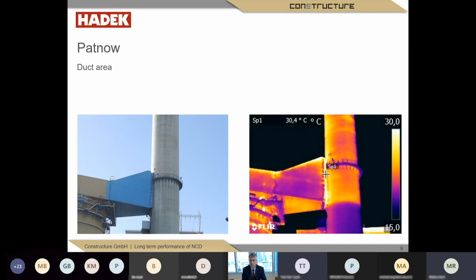On the next page, you can see the thermal imaging of the duct area. What you can clearly see is the area where the inside surface is subject to hot flue gases, because below the hopper, everything is cold. And above you have a uniform temperature distribution on the surface, and we detected no suspicious areas where the Penguard block lining failed. Here in the compensator area, you can see that there is a lack of insulation, and there the temperatures are a little bit higher. But this is not an issue of the Penguard system, but of the compensator.